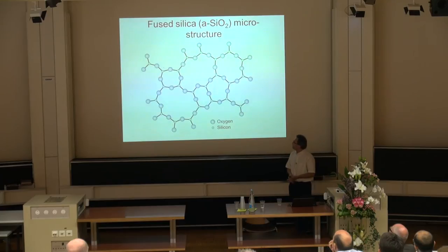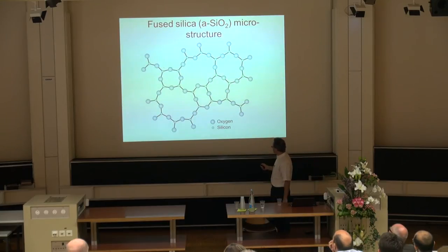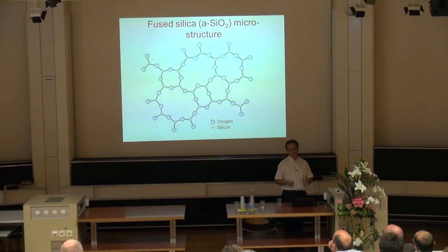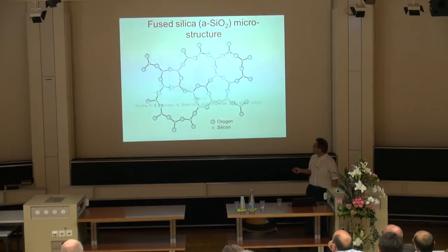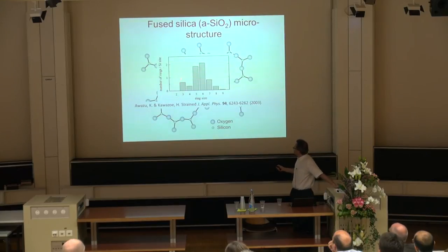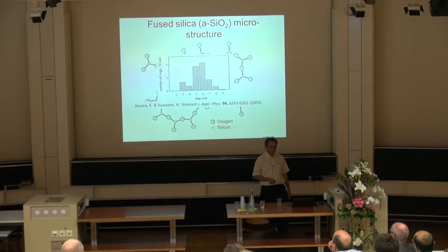And now it's also a fascinating material because it is, what we call amorphous, but it's in fact not really amorphous because it has a short range order. It's not that it's totally disorganized, but of course the ordering is only on the short scale. So you can draw statistics, for instance for silicon oxide, about the size of the rings, how they would distribute in the material, forming something like that.